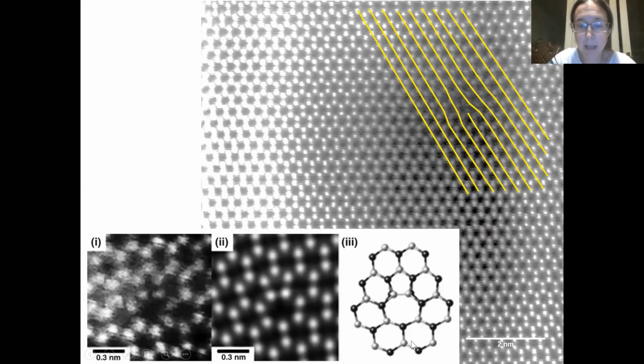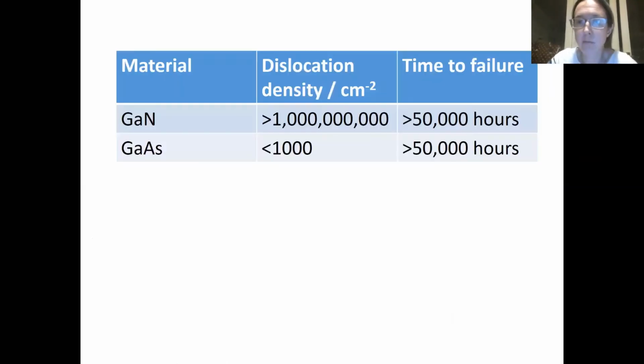This is an example from a paper in the literature. Here's the real image, and here is a nice model of it. And we can see the atomic structure, which is mostly made of these 6-membered rings, going wrong and being disrupted at this part of the dislocation here, the end of this extra half plane. Okay, so why is that a problem? What does that do to the emission of light from our LED? Well, it kind of depends what material you're looking at. In gallium nitride, we have a huge number of these dislocations, these defects. If you look down at the surface of a gallium nitride crystal and counted the ends of the defects emerging from the crystal, you'd find about 1 billion of them in a centimetre squared.